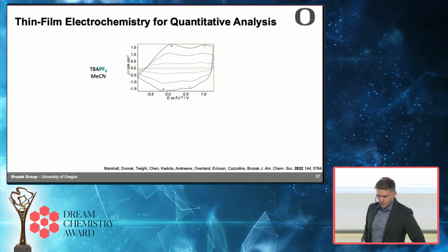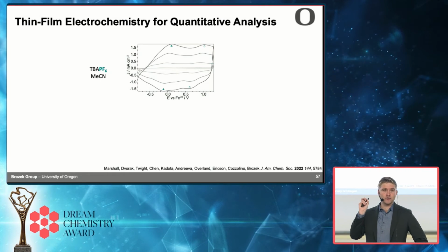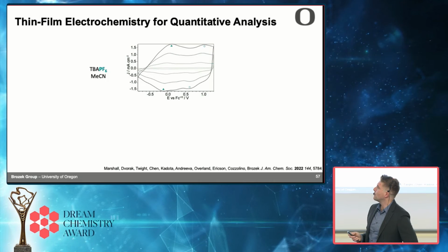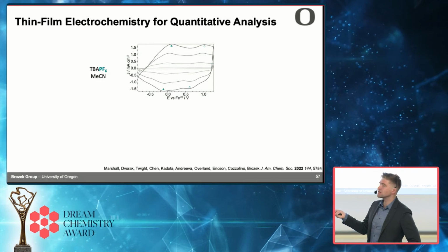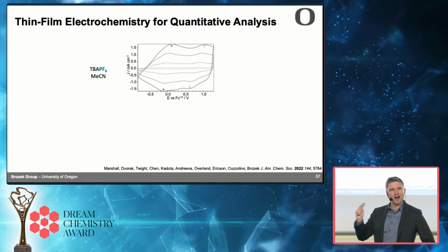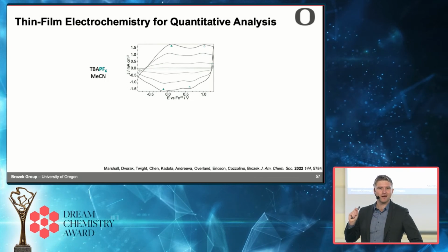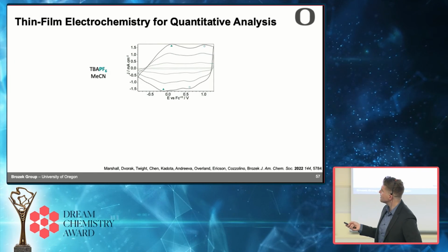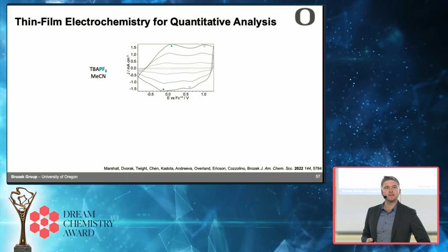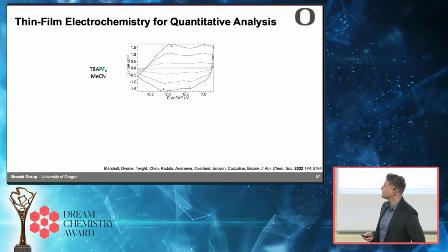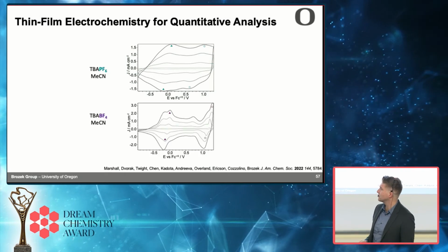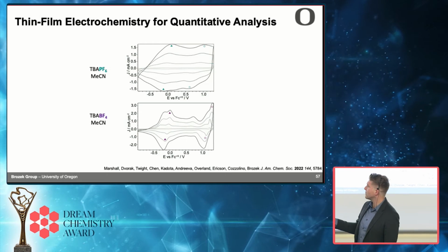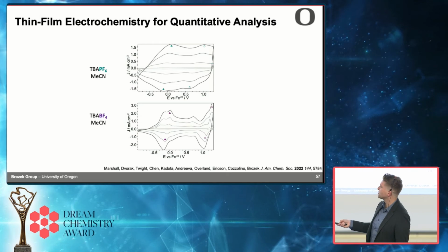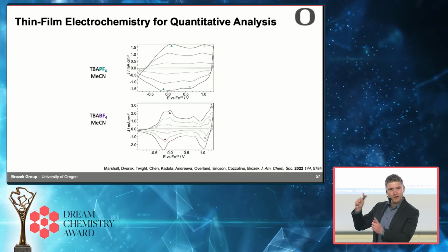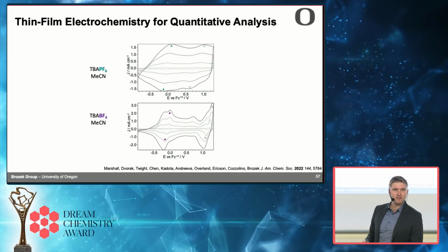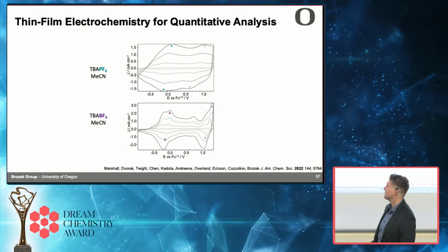And then we started to think, you know, the pore sizes in iron triazolate are really small. How is PF6, our anion in the electrolyte, charge compensating the iron 3+ when we try to oxidize the material? Maybe PF6 simply isn't able to get inside. So we thought, what happens if we move to simply a smaller anion? And so when we move to a smaller anion, BF4, everything changes. The peaks become sharper, there's more of them, and depending on how you assign them, everything shifts to less positive potentials, meaning it becomes easier to oxidize this thing.